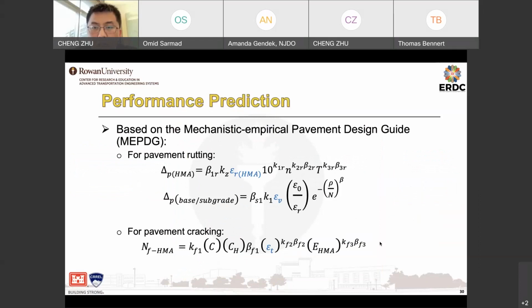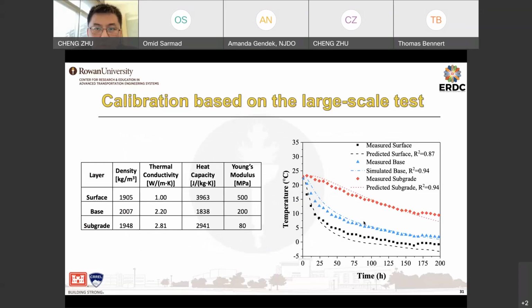After we do the finite element modeling, we use the output to calculate the pavement rutting and cracking. The equations that we use come from the MEPDG. Some of the equations are listed here. And this is the calibration that we did, calibrating our experimental results against the numerical model. The numerical parameters are calibrated so that the predicted temperature at different layers has a good fit with the experimental data. From there, we can get the mechanical and thermal properties, especially the thermal properties of the different layers.